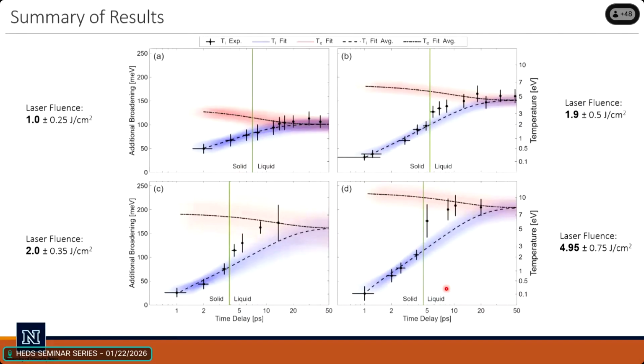Because we have the X-ray diffraction diagnostic as a ride-along for free, we can easily say, when does this sample melt? Because we see the disappearance of the diffraction lines. And so we can add a vertical line to each of these that says when the sample melts. So now we know the temperature versus time of the ions, and we know when the sample melts.